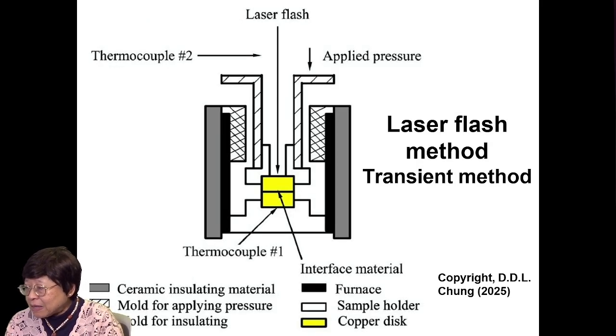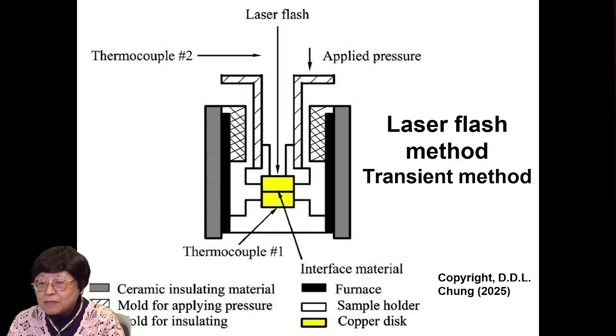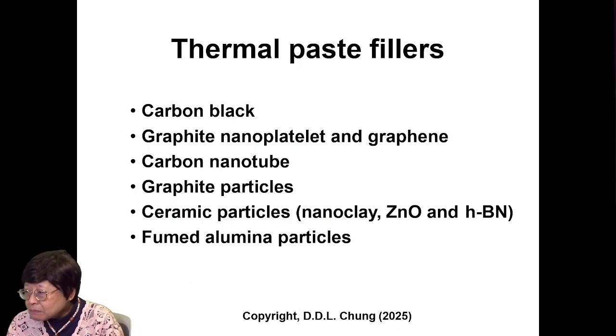The laser flash method is the transient method. You have a pulse of laser flashing on the sandwich. And on the backside of the sandwich is a thermocouple to measure the temperature rise. And the rate of the temperature rise reflects the thermal diffusivity, which relates to the thermal conductivity, or the thermal contact conductance in this case.